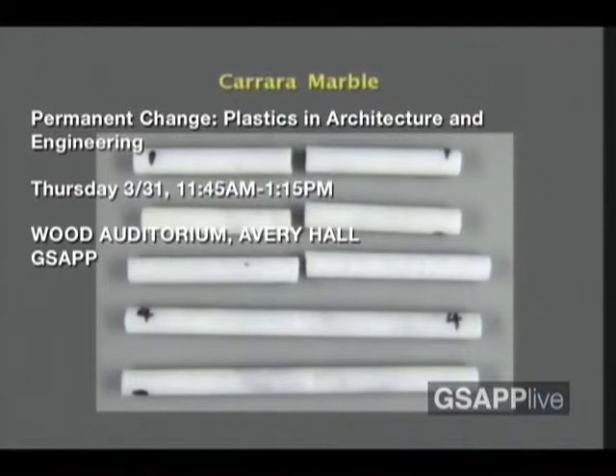This is Carrara marble. By the way, this sculpture is made from probably the most beautiful and uniform piece of Carrara marble I have ever seen. Here's the flexure modulus of Carrara marble, 22 gigapascals, and of course it fails brittly. So we have two different failure modes in materials we're trying to put together, and very different moduli. Here's the failure of Carrara marble, demonstrating its brittle failure. Here's aluminum. Well, we've dropped down the flexure modulus, something a little bit closer to what we might need for marble, but still a little high compared to 22, and of course good ductile and plastic deformation.